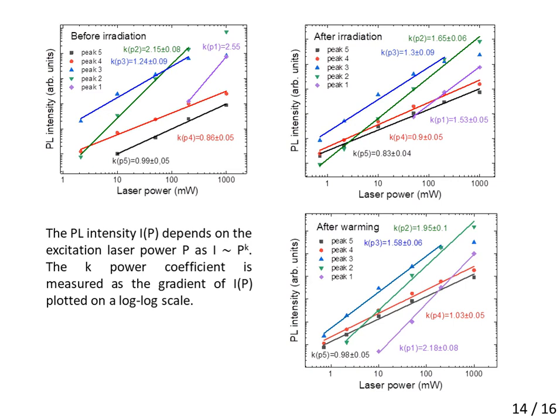Such decomposition also allows us to estimate changes in the intensity of each photoluminescence band. Here you can see the power coefficients, measured as the slope of the intensity dependencies.